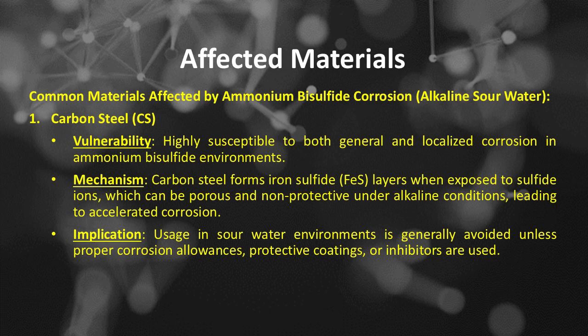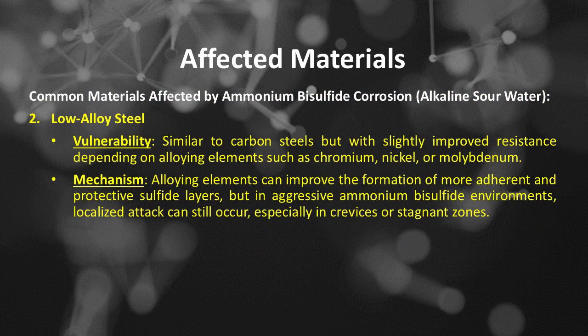Common materials affected by ammonium bisulfide corrosion or alkaline sour water include, number 1, carbon steels. The vulnerability of carbon steel: highly susceptible to both general and localized corrosion in ammonium bisulfide environments. The mechanism: carbon steel forms iron sulfide layers when exposed to sulfide ions, which can be porous and non-protective under alkaline conditions, leading to accelerated corrosion. The implication: carbon steel usage in sour water environments is generally avoided unless proper corrosion allowances, protective coatings, or inhibitors are used.